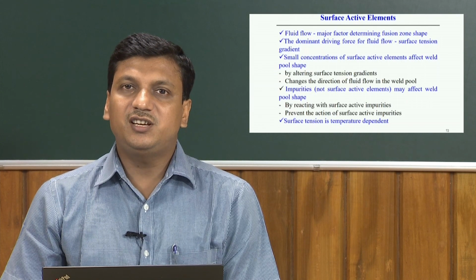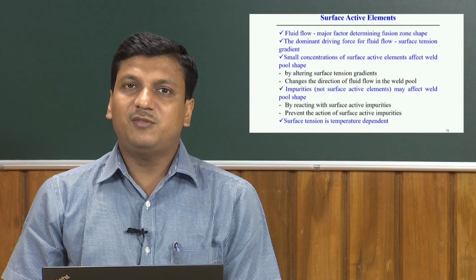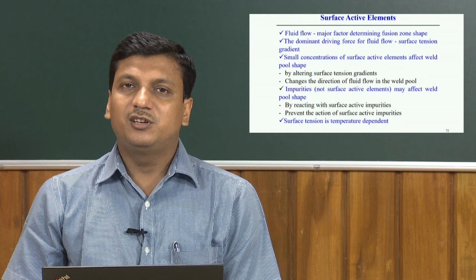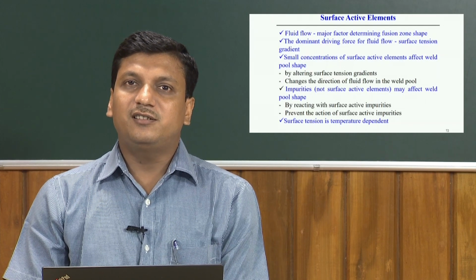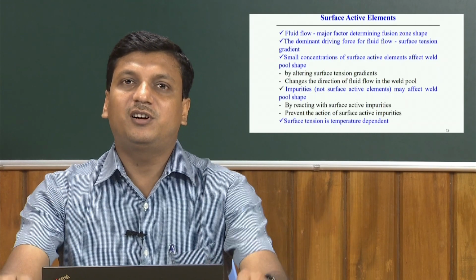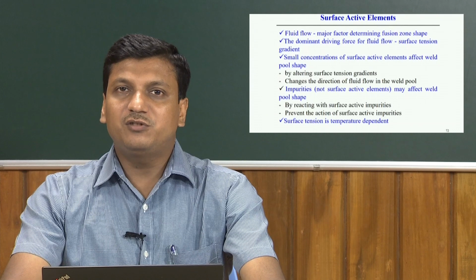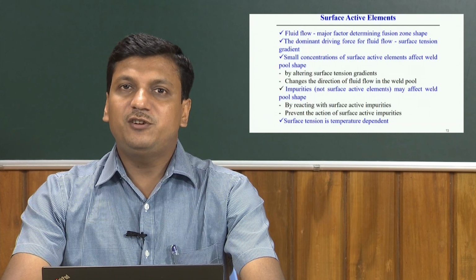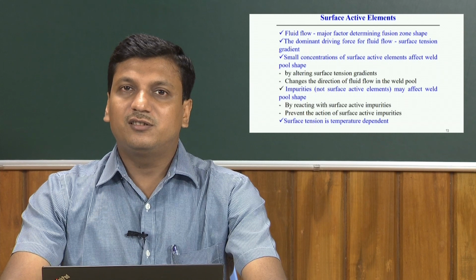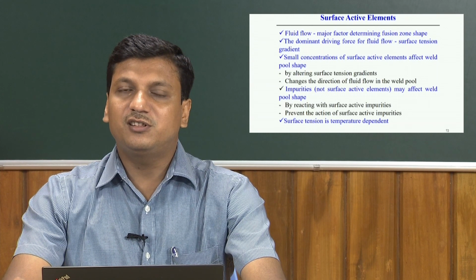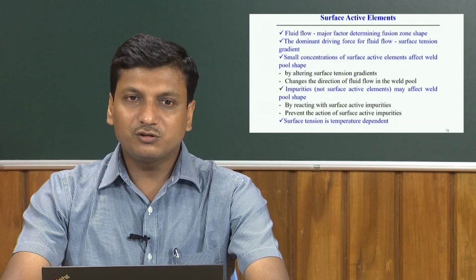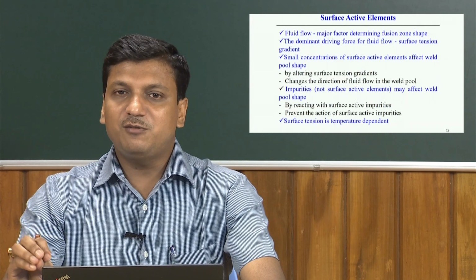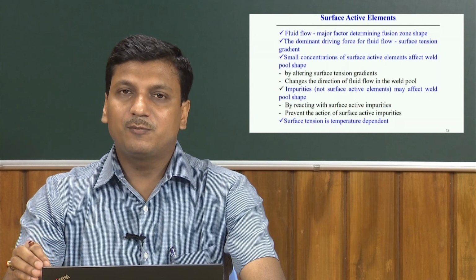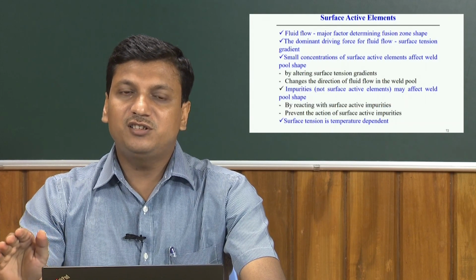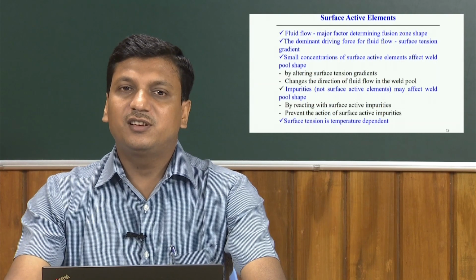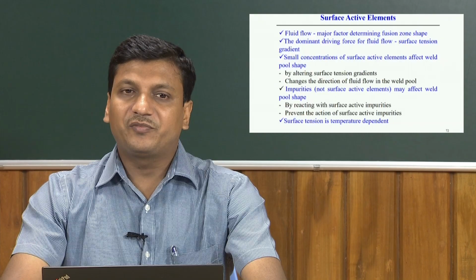and we assume the steel is a binary system of iron plus one surface active element. So, between pure iron and this binary alloy of iron, the nature of the metal flow can differ depending upon the presence of the surface active elements in the second case. So, a small concentration of surface active elements actually affects the shape of the weld pool simply by altering the surface tension gradient. This is one way.